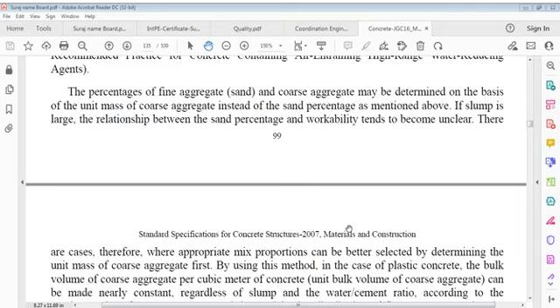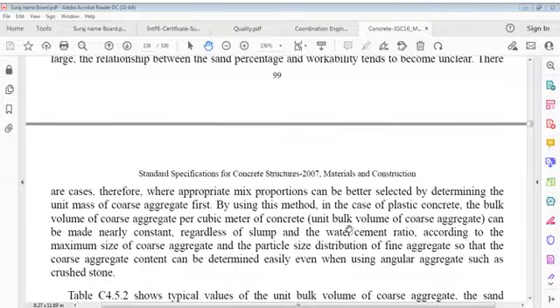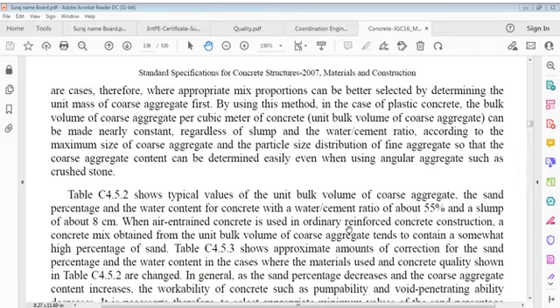If slump is large, the relationship between sand percentage and workability tends to become unclear. There are cases, therefore, where appropriate mix proportions can be better selected by determining the unit mass of coarse aggregate first. By using this method, in case of plastic concrete, the bulk volume of coarse aggregate per cubic meter of concrete, the unit bulk volume of coarse aggregate, can be made nearly constant, regardless of slump and water cement ratio, according to the maximum size of coarse aggregate and particle size distribution of fine aggregate, so that coarse aggregate content can be determined easily even when using angular aggregates such as crushed stone.